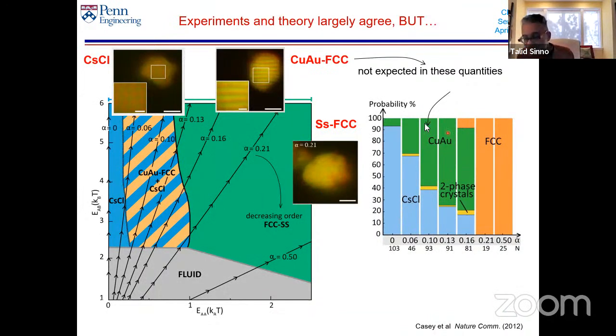And what they ended up doing was counting every crystallite that they saw. So this is a plot of the statistics of what they see. As I go from this line, this is an alpha of 0.06, that means I have 6% mixing. At 0.06, most of the crystallites I see are cesium chloride, and I see a few of these copper gold. As I go to 0.1, which is this one, fewer crystallites are cesium chloride, and more of them are copper gold. And then I'll keep going.